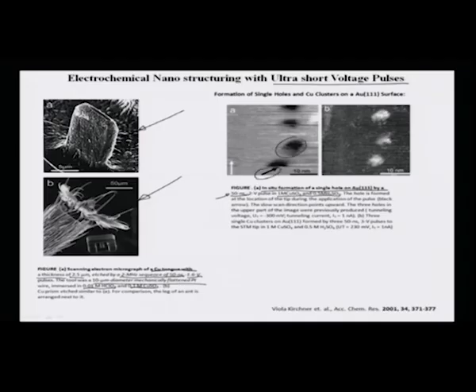The initiation of the hole formation process has been shown in this particular schematic photograph, and you can see that there are about 3 single copper clusters on gold formed by 3 50 nanosecond 3 volt pulses to the STM tip, again in the same electrolyte solution. Due to the formation of this kind of copper so called electrode, you can have an inverted feature hole created as in figure A. But what is important for me to tell you is the resolution here. This is being done at a resolution of 10 nanometers, which is way beyond what you have seen so far.